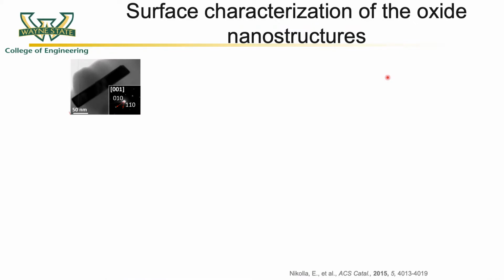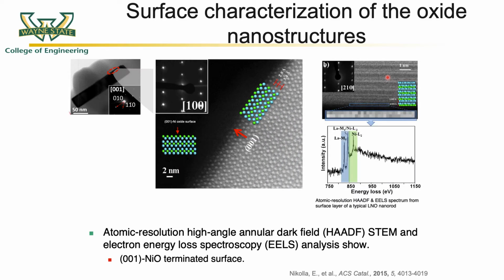To further characterize the surface structure of these rod-shaped nanostructures, we use high-angle annular dark field imaging using scanning transmission electron microscopy. Selected area electron diffraction measurements indicate the formation of 001 surface termination on these oxides.